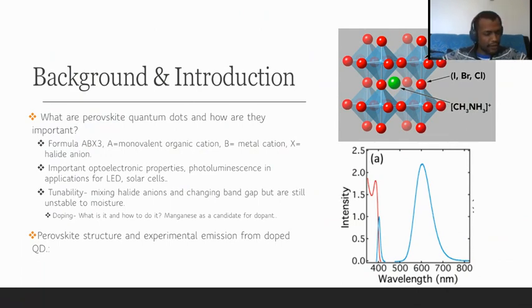Because they offer a lot of important optoelectronic properties, including high quantum yield photoluminescence, that can be used in a variety of applications, including LEDs and solar cells. They also offer a high degree of tunability by mixing halide anions, but they still have problems because they are unstable in moisture. So a good solution for that would be the doping of the material. And the doping is basically introducing a small degree of impurity to improve the properties. So this will enhance the optoelectronic properties and make the nanocrystal stable as well. And manganese is actually a good dopant for this type of nanocrystals.